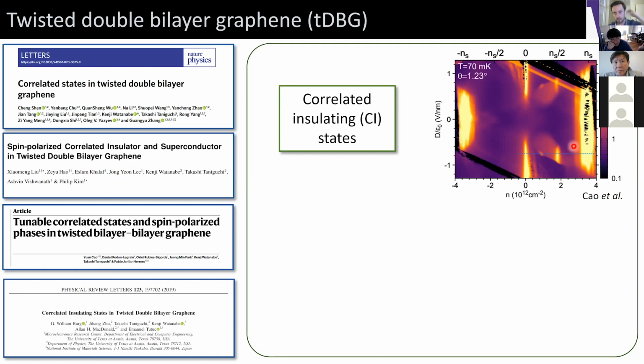And then they see the emergence of these correlated insulating states, most strongly at half filling of the conduction band, and then also more weakly under certain conditions at quarter and 3/4 filling, surrounded by this kind of odd halo-like feature marked by increased resistivity.